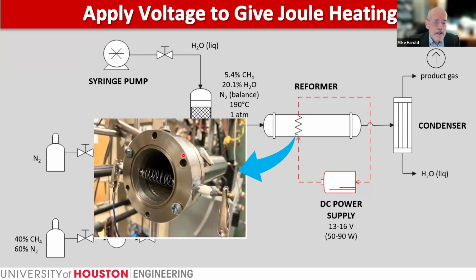This is not a well-designed reactor. When you look at it immediately, you can see that there are potential regions for bypassing. Just envision that the ultimate reactor would be a staggered line of these coils down the length of the tube. The experiments we carried out have been so far with a single coil. So we apply a DC voltage in the range of 13 to 16 volts. That produces a power, for the given resistance of the FeCrAl, of between 50 and 90 watts. We then collect the effluent and characterize the unreacted methane, the produced CO and CO2.